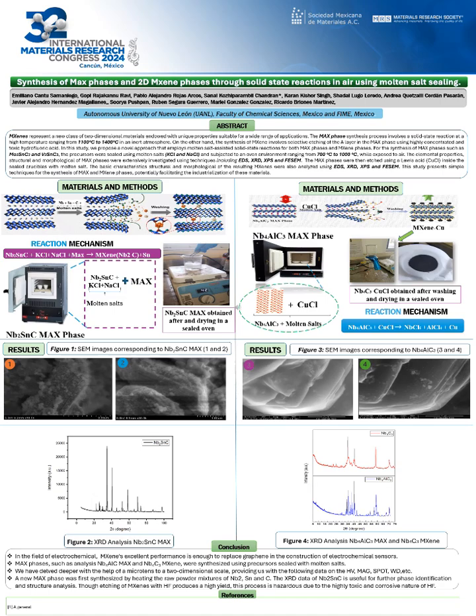adjacent to figure 4, we can understand that the XRD pattern confirms the analysis of Nb4AlC3, confirming the hexagonal MAX phase, and the XRD pattern that is formed by the formation of the MXene, in which the peak corresponding to the Al around 37.2 degrees has disappeared. Also, on the left side of the poster, we can see the XRD pattern of Nb2SnC, that confirms the formation of hexagonal crystal structure MAX phases, which is in line with the standard ICSD files reported.